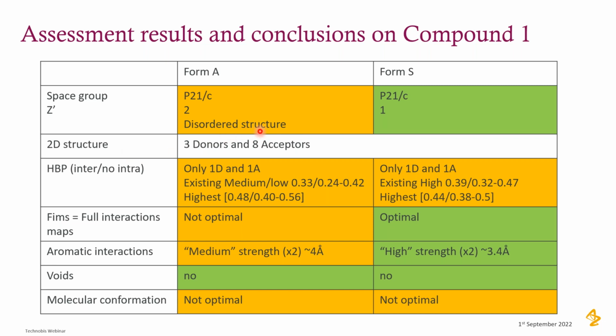You've got in 4A a disordered structure. The 2D structure contains, as I said to you, 3 donors and 8 acceptors. In terms of H-bond propensity, we basically have still only 1 donor and acceptor in both. But for 4S, you've got the highest propensity of the one actually existing. In terms of geometry, how they are in the crystal structure, they are geometrically non-optimal in 4A, as we've seen from the full interaction maps, but it is a lot more optimal in 4S.